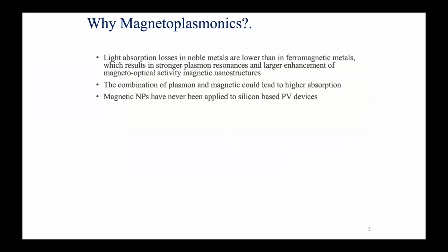So why magneto plasmonics? Light absorption losses in noble metals are usually lower than in ferromagnetic metals, which results in stronger plasmon resonances and larger enhancement of magneto-optical activity in magnetic structures. So we propose that the combination of plasmon and magnetic nanoparticles could lead to higher absorption. Magnetic nanoparticles haven't been applied to silicon-based PV devices.